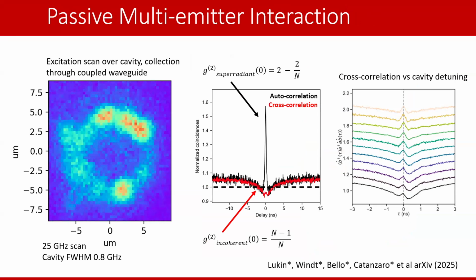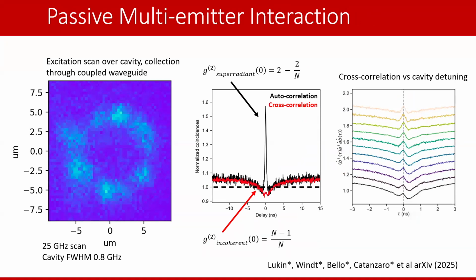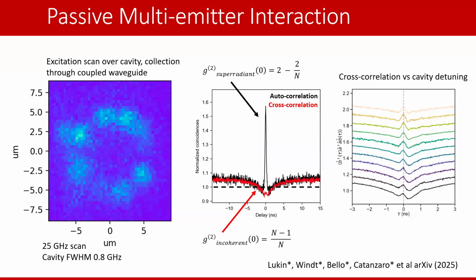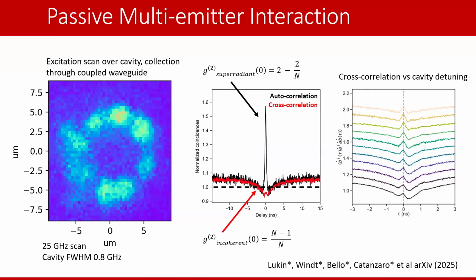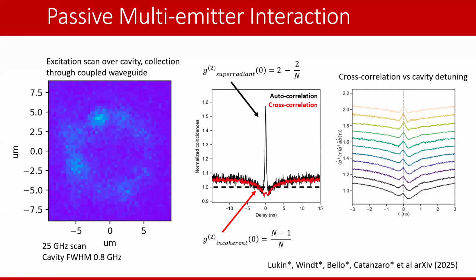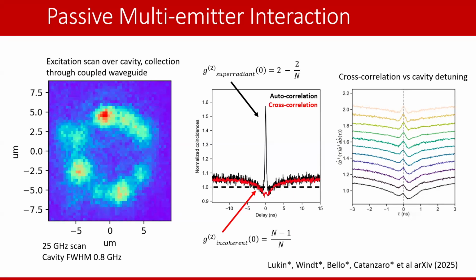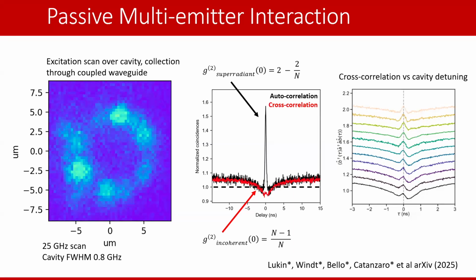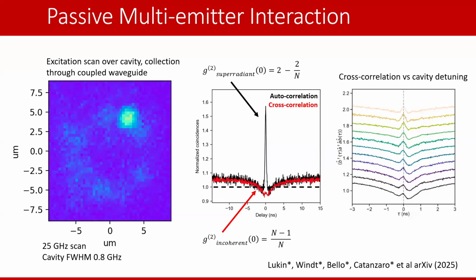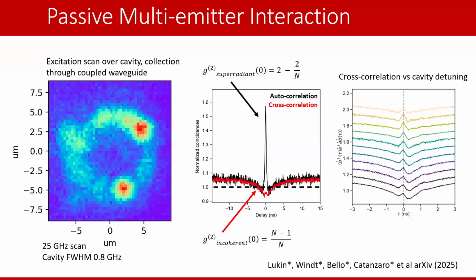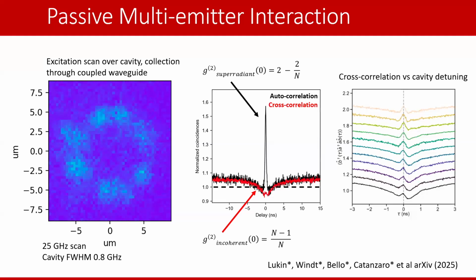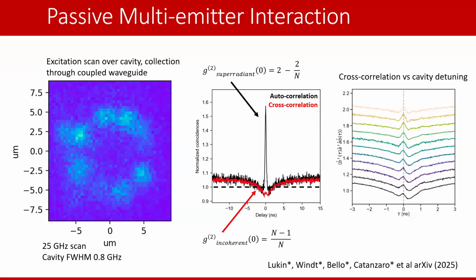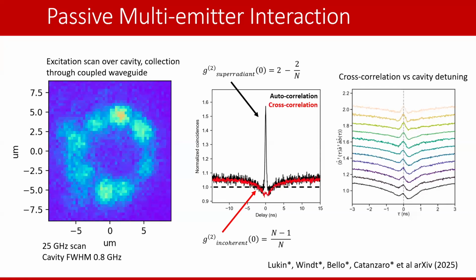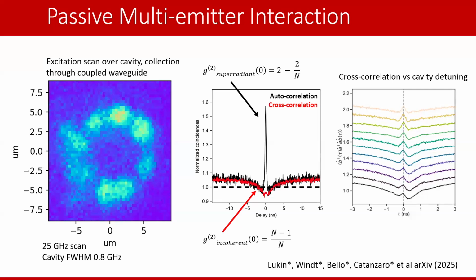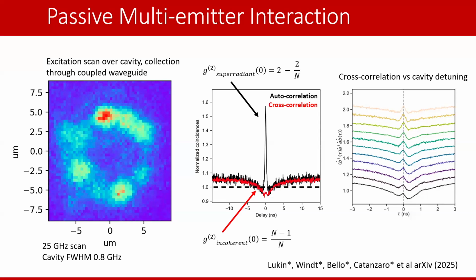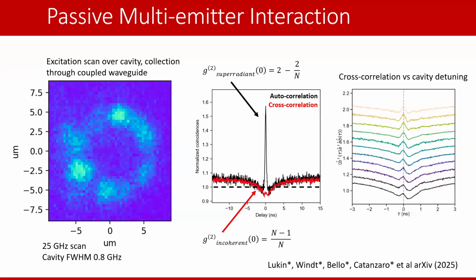So what you're seeing here in this nice movie is a waveguide coupled to this whispering gallery mode resonator. There are between 5 to 10 to even 17 defects within this resonator. And you can kind of see that from the autocorrelation and cross-correlation measurements that we've taken off of photons going into the clockwise and counterclockwise modes of this resonator. This movie is actually a raster scan of above-resonant light excitation to the cavity, collected out of the coupled waveguide. By collecting out of the coupled waveguide, you get this spatial match, because when the laser's over here, it's exciting the defect, and then the defect's photoluminescence is projected into the cavity and then out.